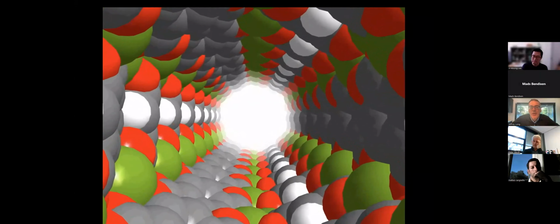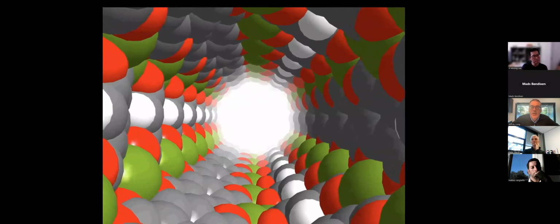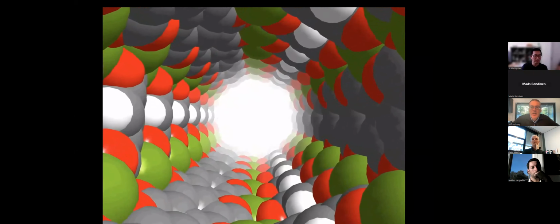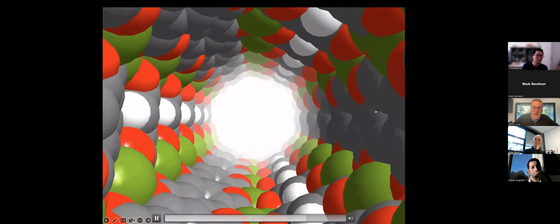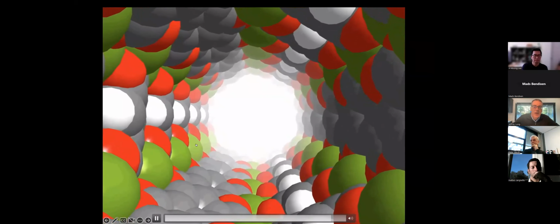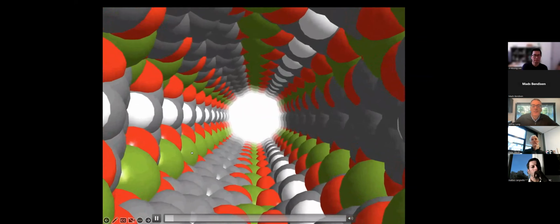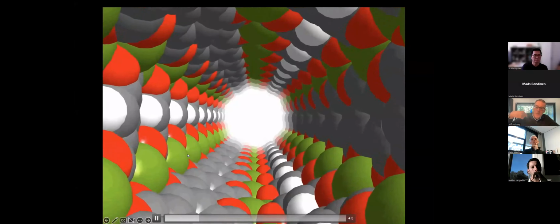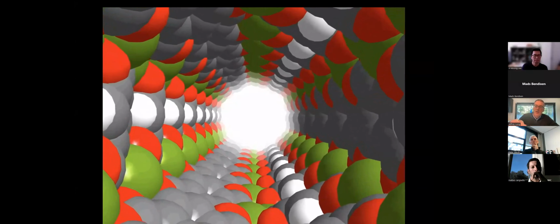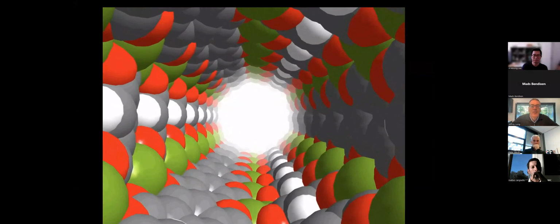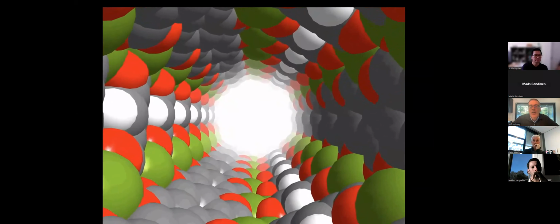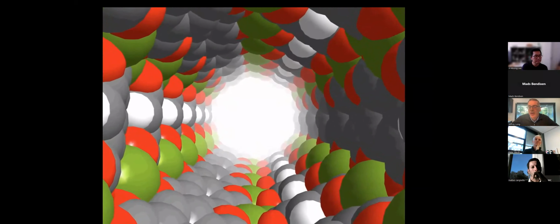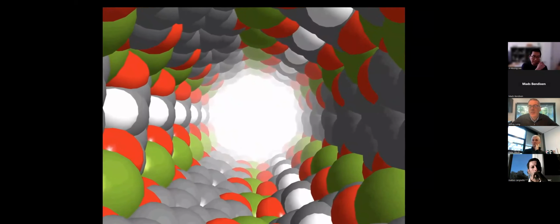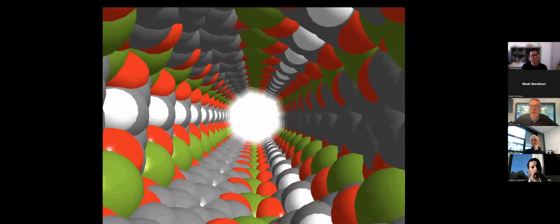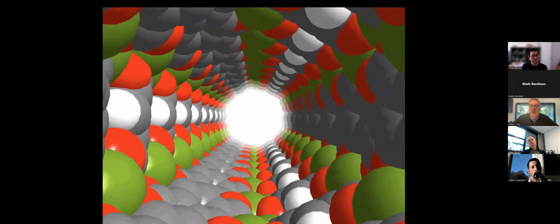And to capture CO2, what we did is we added a diamine, one diamine like ethylene diamine, to every magnesium center shown in green. And that creates rows of magnesium diamine running along the corners of each channel. And it turns out that the spacing for those chains are just right to polymerize CO2 into ammonium carbamate, one-dimensional solid.